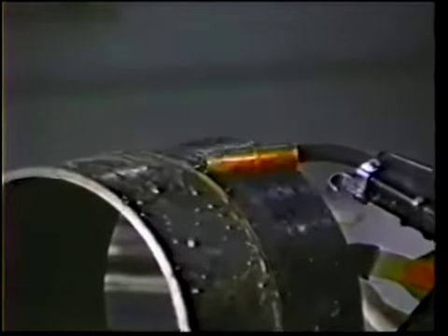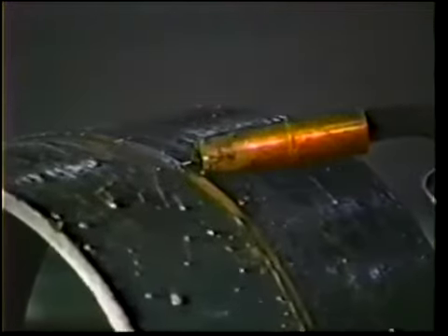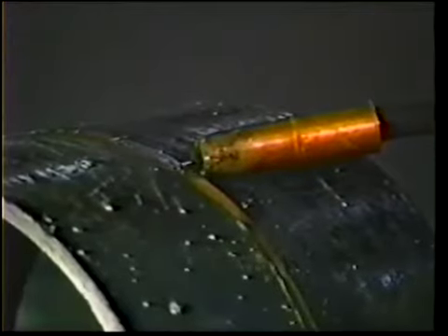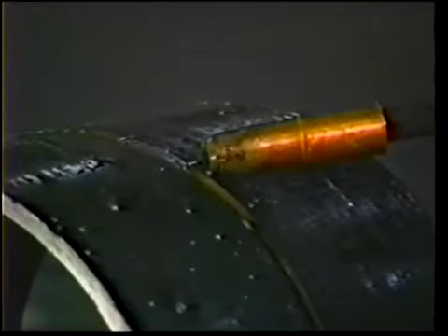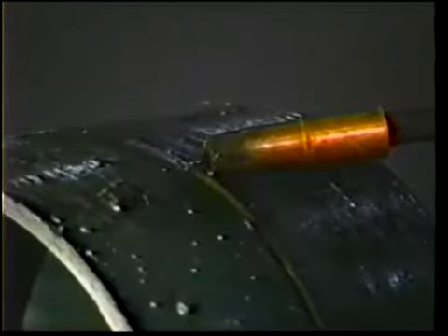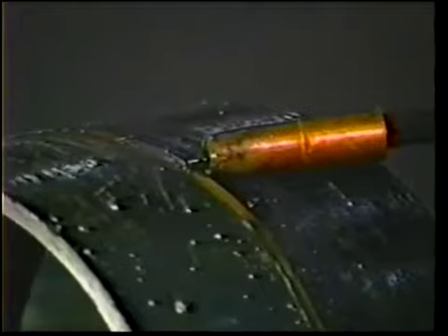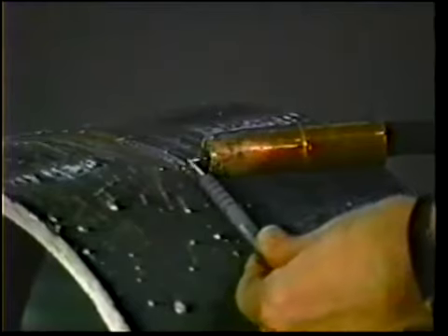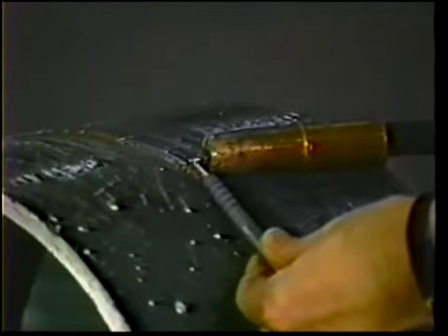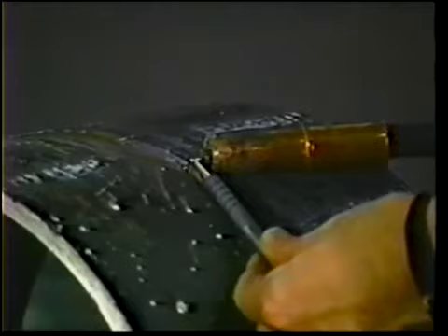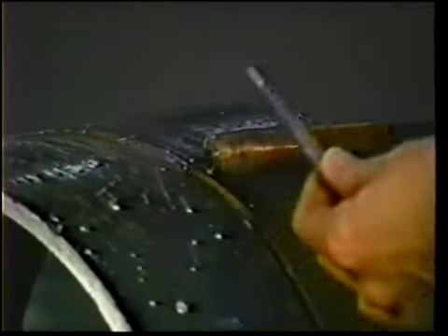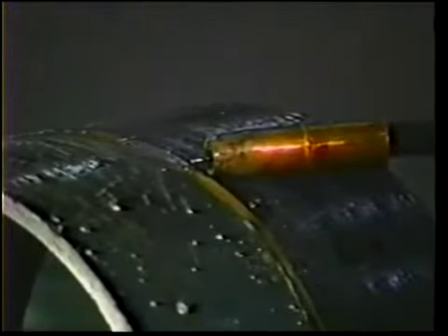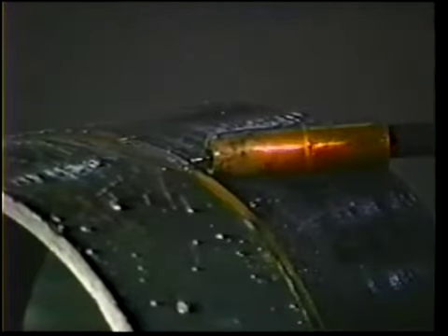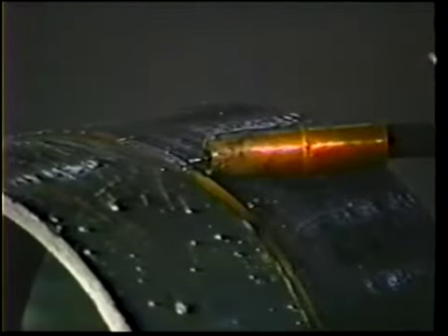It doesn't matter whether you're welding a pipe or a piece of sheet metal, you're going to use short-circuit welding. And in short-circuit welding, particularly on quality work, on code work, and on very thin sheet metals, wire stick-out becomes critical. Notice on this pipe application that the wire stick-out is approximately 3/16 of an inch. By keeping the wire stick-out small like this, I can use the minimum amount of voltage, which on an application like this is usually around 17 or 18 volts.